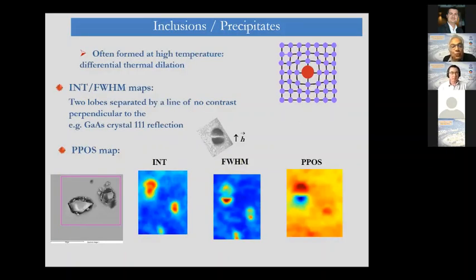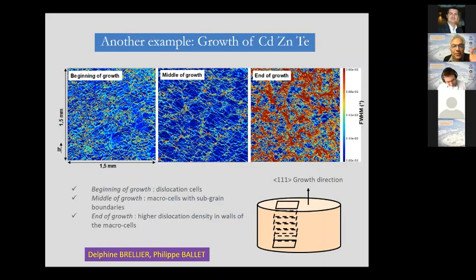The same if you look at inclusions, precipitates, you have signatures on the integrated intensity, full width half maximum, and peak position. And these inclusions appear as a double lobe like that. And you can identify in this way very easily the inclusions.